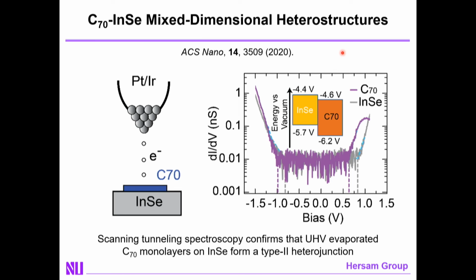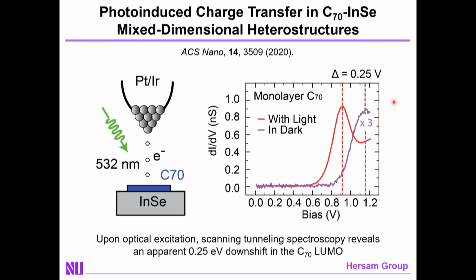Another advantage of doing this in ultra-high vacuum is that you can then probe, using scanning tunneling spectroscopy, what indeed the energy level locations are. And we see that the scanning tunneling spectroscopy confirms the simple band picture that is shown schematically here. What we then do is we take that system, we shine light on it, we measure with scanning tunneling spectroscopy any shifts that occur in the electronic density of states. And what you observe is a very obvious shifting. This is the peak affiliated with the lowest unoccupied molecular orbital of C70, which you would typically think should not vary as a function of optical irradiation. And yet we see very clearly in scanning tunneling spectroscopy a shift on the order of 250 millivolts, which is quite significant and well above kT at room temperature.